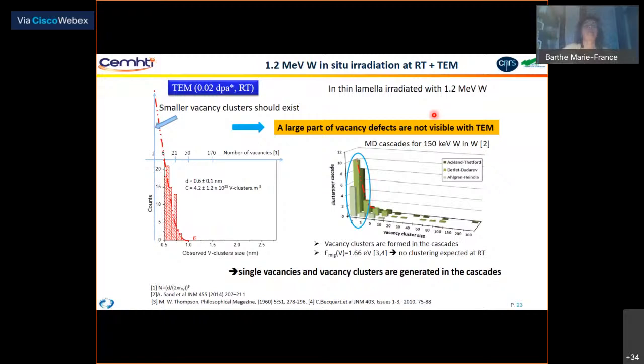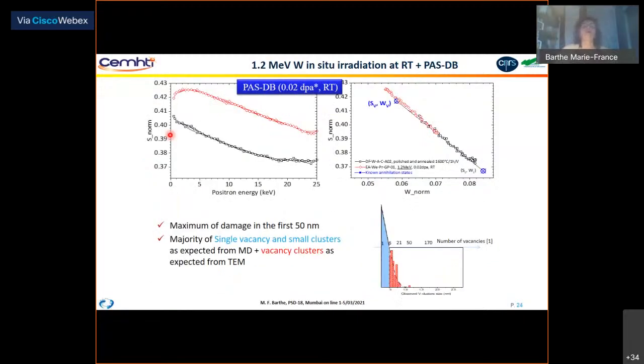So we have used positrons and measured the S as a function of the energy in the same type of irradiated sample. And we can see here that the SW point is very close to the one for the single vacancy. So we can say that the majority of single vacancies are detected in this sample, and also some small clusters because we are a little bit higher above this point. So we see, as in TEM, the vacancy clusters and also, of course, single vacancies with positrons.